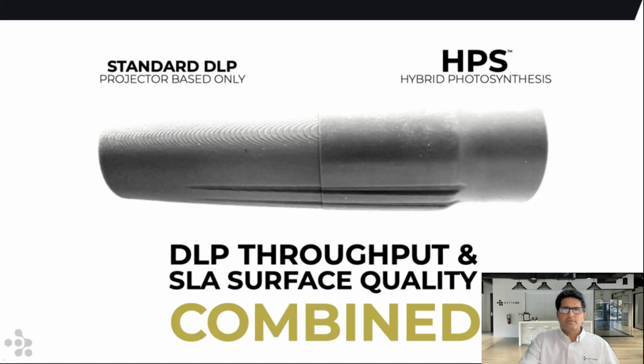Second, quite obvious is really the surface that you see here. When you see this surface, precise organic surfaces, which means there's no post-finishing required on this part. The section of the part you see on the left is what you typically get out of a DLP or a projector-based system. And the part that you see on the right is what HPS gives you, which means you're not only benefiting from the high throughput when printing, but if you are doing organic shapes with jewelry or dental or any other applications, connectors perhaps, you never have to finish these parts because all these organic shapes and flat surfaces are very precise coming off the machine.